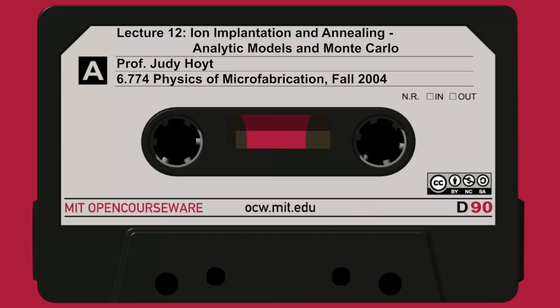So let's go on to slide 20 and talk about a real profile. Real profiles are not perfectly Gaussian. In some cases, they're more Gaussian than others, but they're generally more complex. If we look at the profile for a light ion, and now light means very light compared to silicon, say boron, these light ions tend to backscatter. Imagine you have a big, heavy bowling ball, and you're throwing a ping pong ball at it. That's the boron. It's a ping pong ball. Well, a lot of those boron atoms go ping right back, right? A few of them will scatter forward, but a lot of them can come right back.